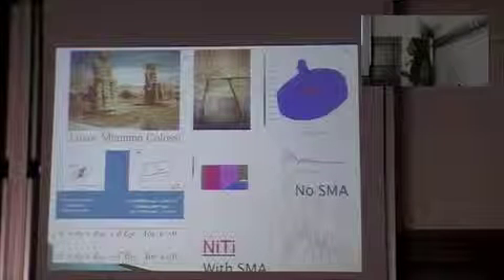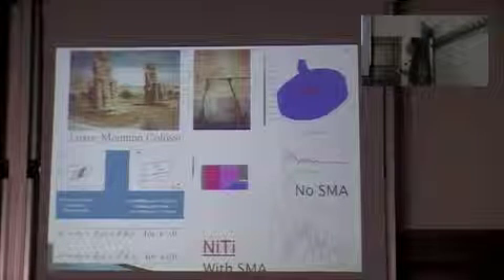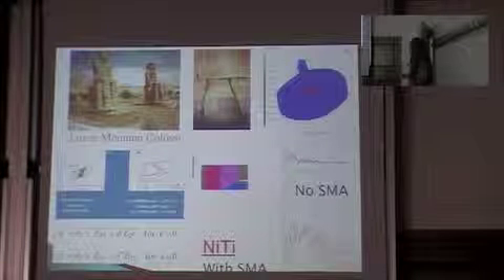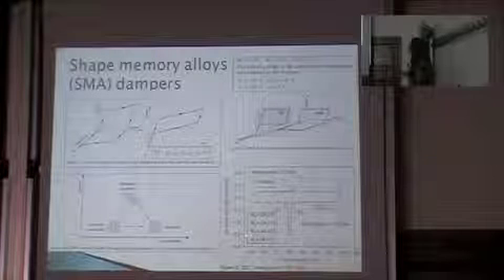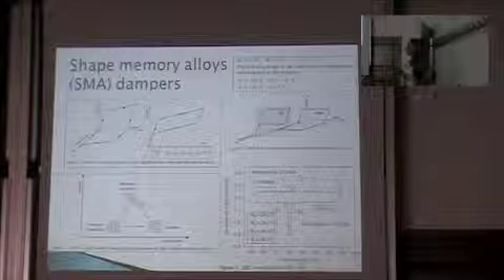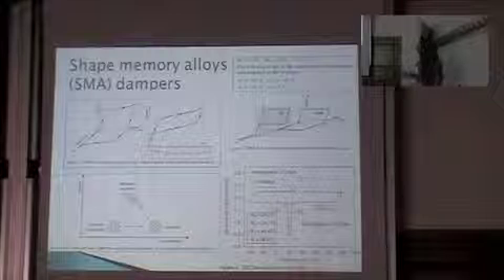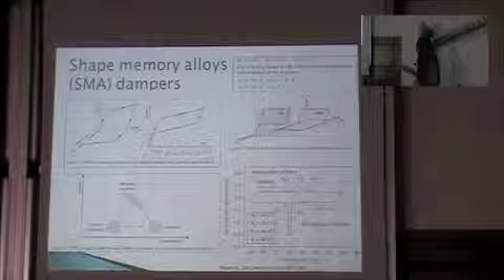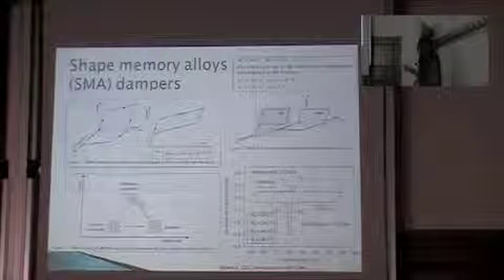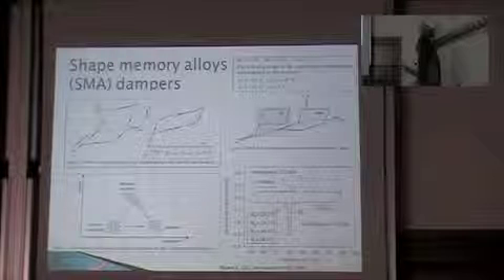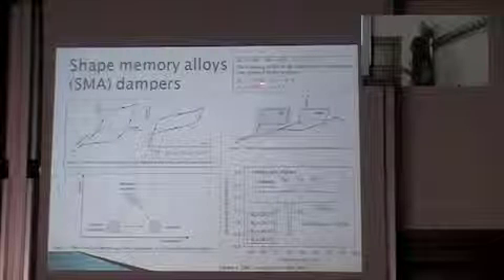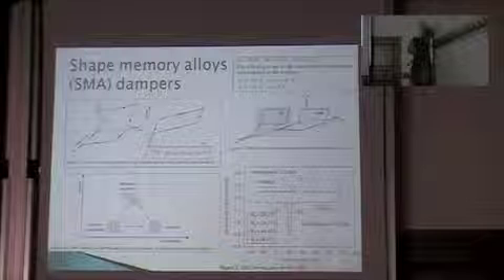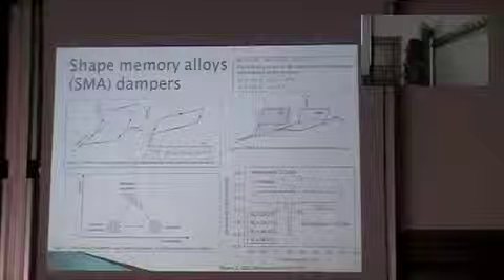But we have the drawback that nickel-titanium only works in this austenite window, which is not very suitable, especially in the desert, which has very big gradients from the night to the day. So we moved to study the behavior of the copper-based alloy, which has a better austenite window in which we can exploit the superelastic properties.